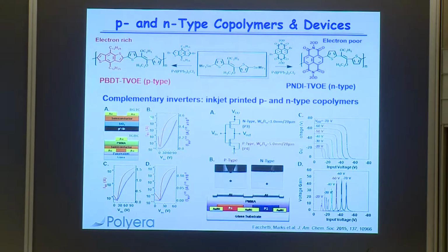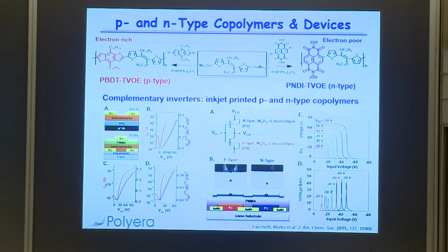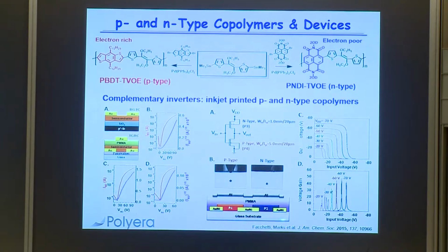You can make two kinds of transistors. This is one where this is called a bottom gate, top contact, gold contacts. Bottom gate is silicon here. And this is a top gate, bottom contact structure. And we can make p-type transistors from this one and n-type transistors from this one. We can inkjet them, and this is a side view just showing the little droplets being inkjetted onto the contacts here. So this is this kind of structure here, architecture here, and we get a quite reasonable complementary inverter. So by having both n and p-type electronics, you get much higher operating frequencies and lower power consumption.